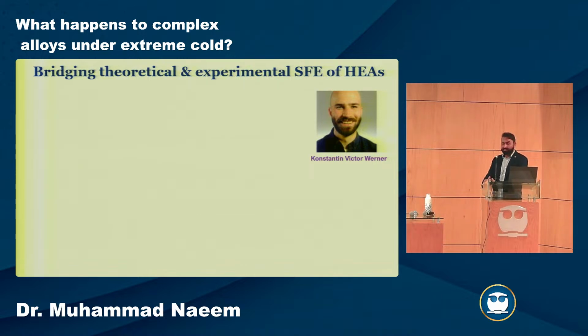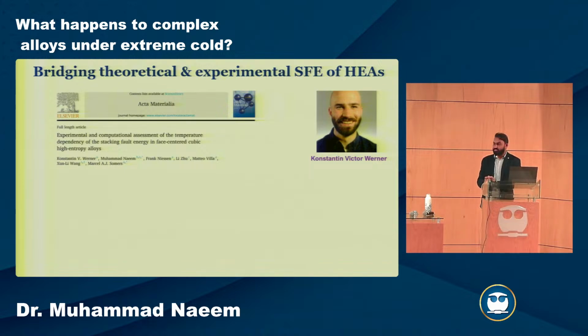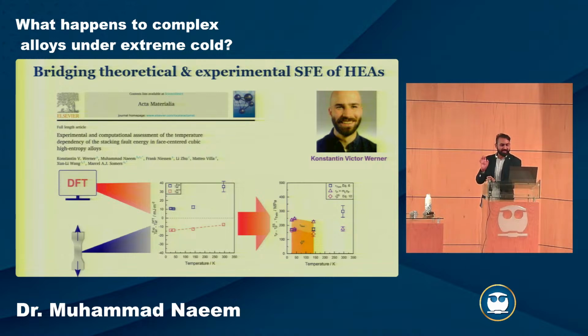So this was student Konstantin who was working on this, and it was ultimately part of his thesis. We have this work just published, actually fresh out of the oven, published last week, and we were very happy about it. I will not go into detail, but basically we combine DFT and in situ experiments, because otherwise you have to do a lot of experiments with TEM samples, and you have to see which mechanism is coming, and you deform in steps. But in this case, in situ, we try to bridge this gap between positive values from diffraction and negative values from DFT.